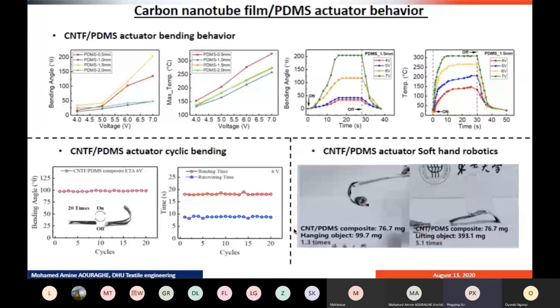In time, the actuator of 1.5 mm in thickness reached its bending state within 17 seconds and remained stable before cutting off the current, and returned to its initial state within 10 seconds. The bending angles also increased with the voltage from 50 degrees to 200 degrees as the temperature increased and the applied voltage went from 4 to 7 volts.